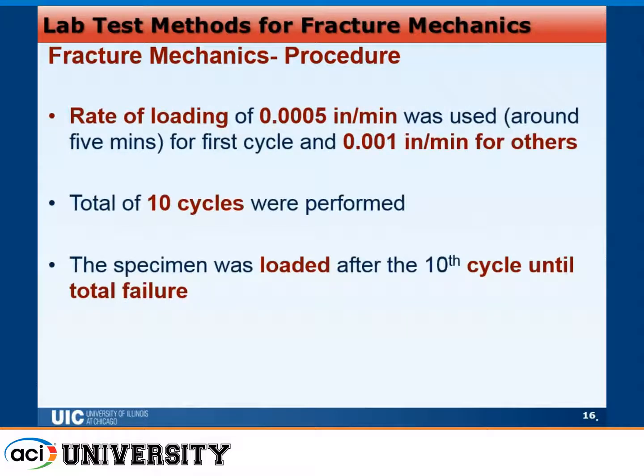The rate was 0.0005, which is very slow CMOD loading, not displacement loading, for the first cycle, which was designed to be around 5 minutes per cycle. For the rest of the cycles, after the crack initiated, we did not have to go as slow, so we doubled it. A total of 10 cycles of loading and unloading was done, and after that, the specimen was taken to failure. The reason we do that is to control the crack propagation as we go in the testing, to be able to calculate all those fracture mechanics parameters.